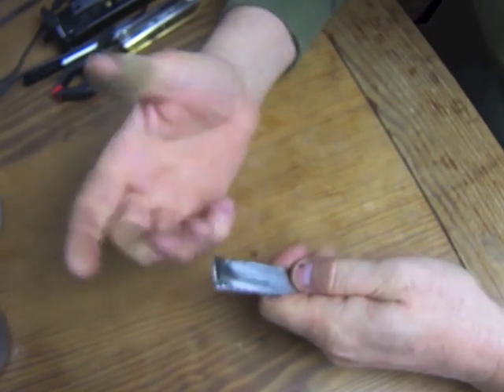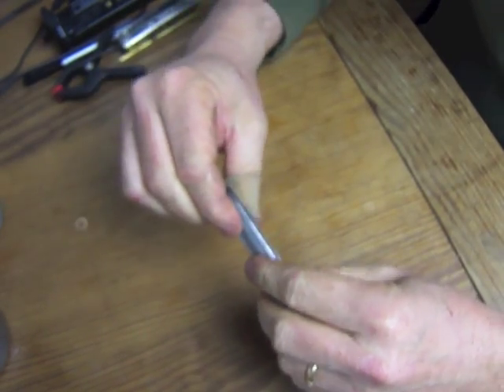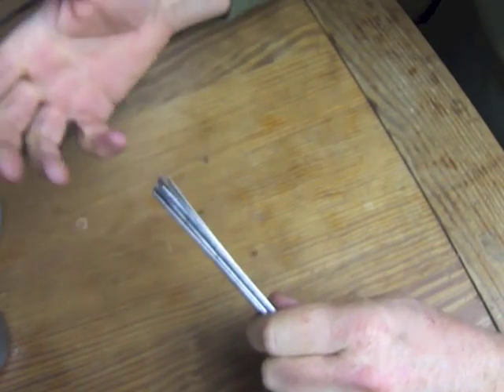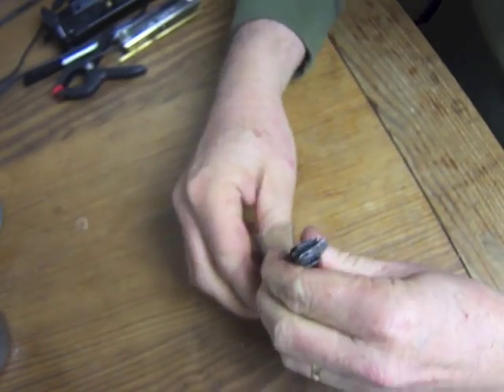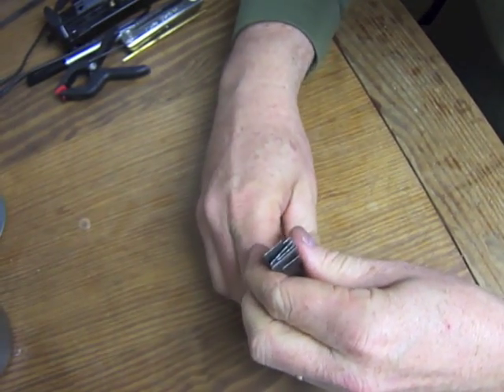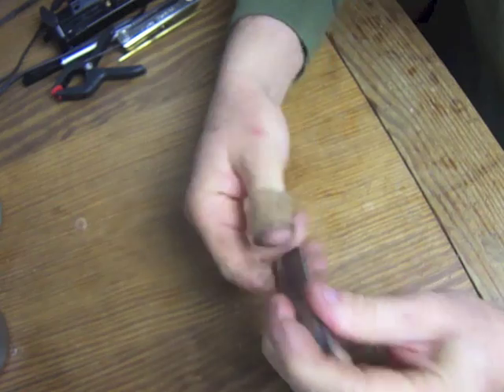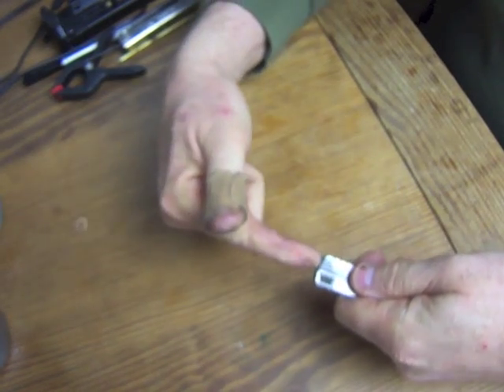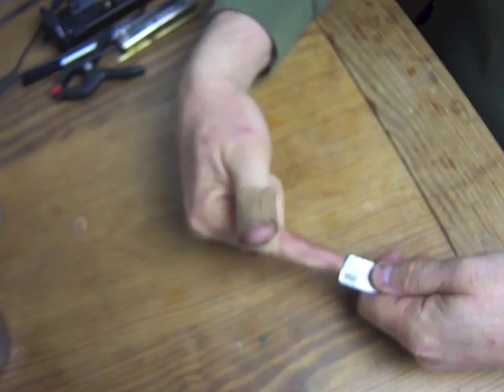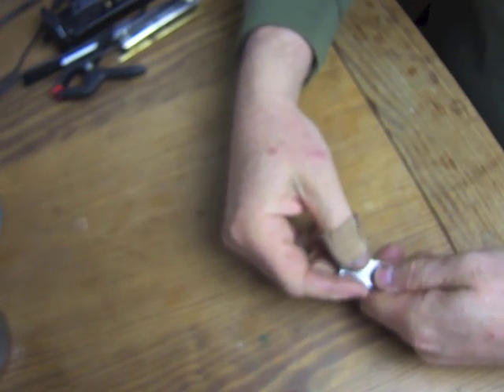So, and then the only difficulty with that is you have to hold it in a pair of tongs when you're welding it. If you have a welder, you can tack it, and then you can weld a piece of rebar on here for a handle, and that makes things certainly easier.